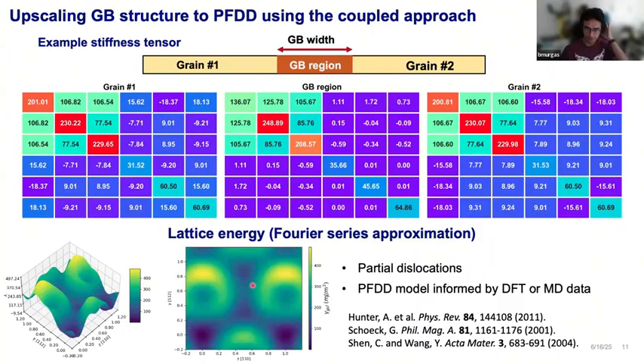The lattice energy is pretty important here because we want to use partial dislocations. If we want to use partial dislocations, we are also using the Fourier series approximation. So this lattice energy, this gamma surface, is computed or informed by DFT or molecular dynamics. And this is important because we use partial dislocations, since the interactions between your grain boundary and your dislocation can change. Instead of being fully transmitted, your partial dislocation can dissociate into a leading and a trail dislocation.